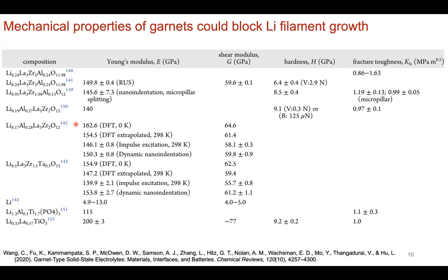Okay, so we left off talking about mechanical properties of these garnets, why initially they were looked at as really promising materials for not only high ionic conductivity, but also chemical stability against lithium and blocking lithium filament growth, right? You probably have heard of lithium dendrite growth, but of course, dendritic formation is a thermodynamic solidification procedure. So if you're not operating in the liquid phase and you're not solidifying, you're really growing filaments. So that's why I use the term lithium filament as opposed to just lithium dendrite specifically.